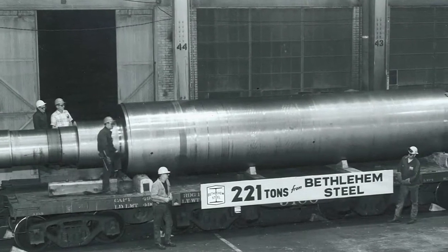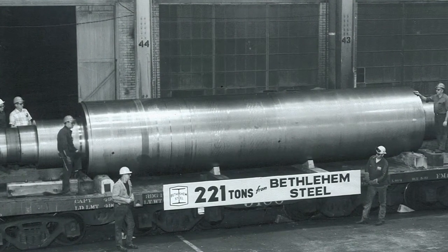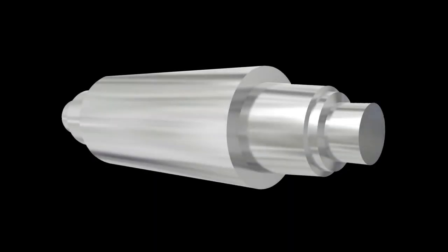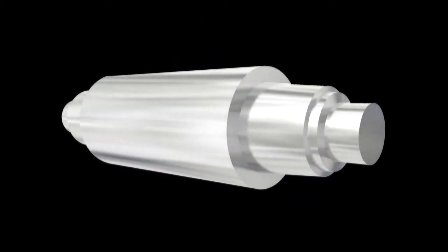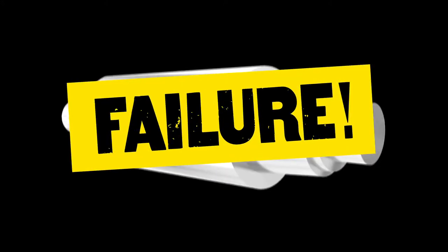Forgings can sometimes weigh over 150 tons, and this process is important because even a few atoms of hydrogen present in a highly forged steel component can lead to catastrophic failure.